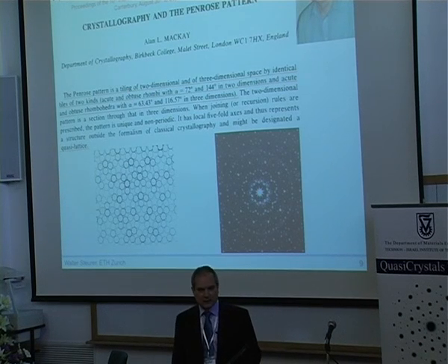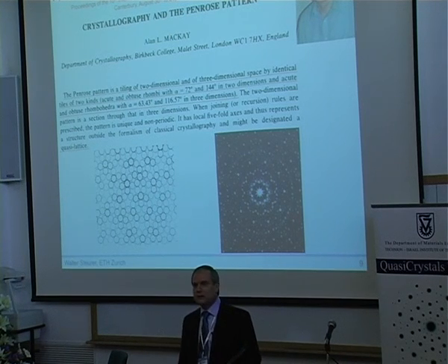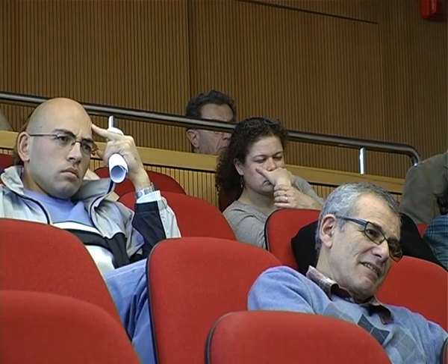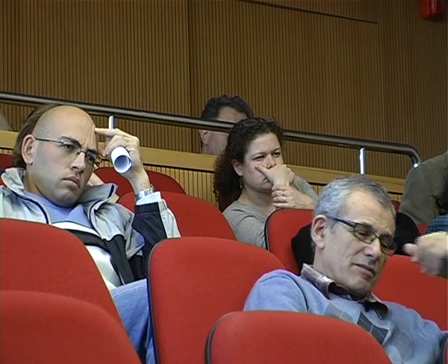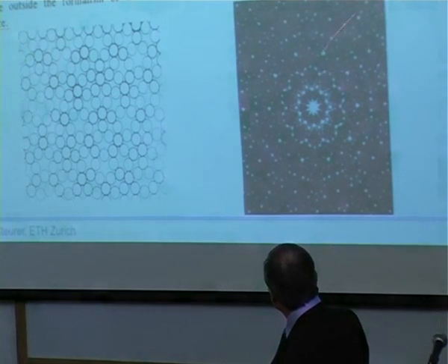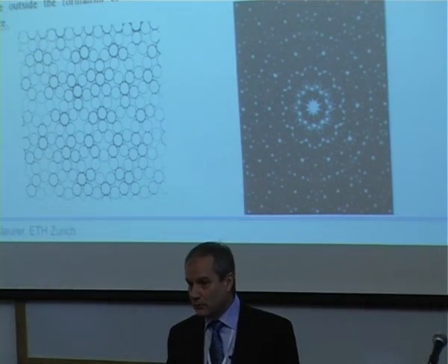Well, and then Alan Mackay, in the beginning of the 80s, he read Scientific American, and he got interested in looking at what kind of diffraction pattern these quasi-lattices, these Penrose tilings, would form. Yeah? If you have a periodic structure, you always get a diffraction pattern which shows sharp Bragg spots on a reciprocal lattice. And he tried what happens if he does an optical transform of such a Penrose tiling. This was the underlying Penrose tiling, and this is the diffraction pattern, and it clearly shows sharp Bragg spots and tenfold symmetry.